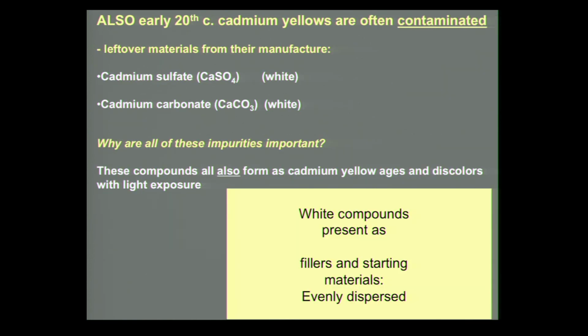And it turns out that the cadmium yellow paints from the turn of the 20th century were also contaminated, and this contamination was actually leftover materials from their manufacture. Typically, cadmium yellow would be prepared with either cadmium sulfate or cadmium carbonate, both of which were white compounds. And the reason why it's so important to know about all these impurities is that all of these compounds also form when cadmium yellow fades over time.